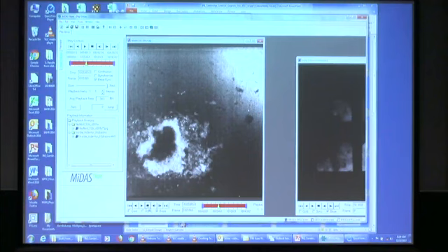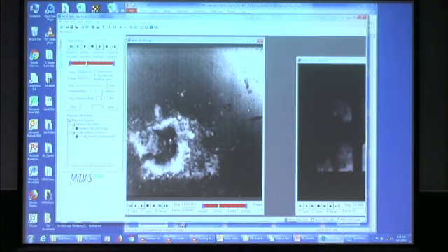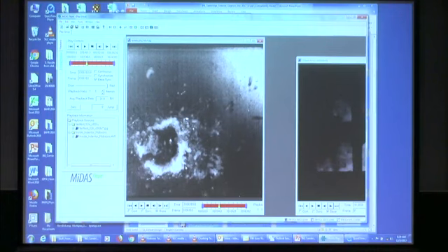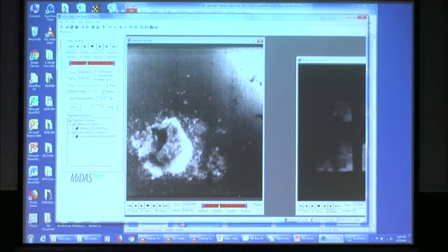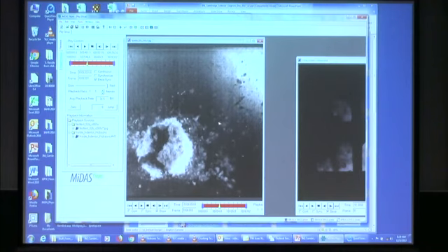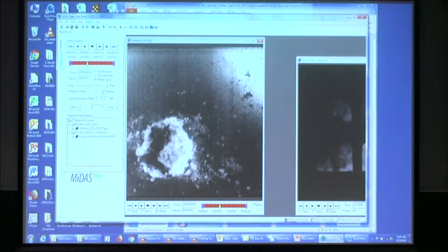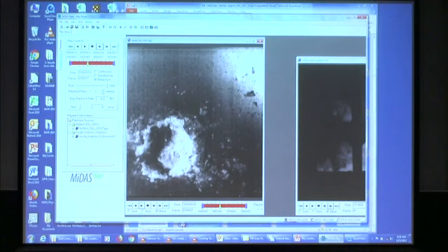And what you will see when we run this is spallation events. Every time one occurs, the big one occurred there, but you still have the remaining ice intact. And every time a spallation event happens, you have this drop in the load.